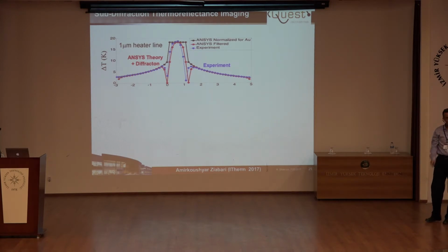So again, Fourier works quite well, up to 1 micron heater. And because of diffraction, what I call filters, the effect of diffraction, and because of the sign change, there is a zero crossing. The red is the modeling, which has been blurred, and the blue is the experiment, and the two match quite well, and the temperature on top of a device matches quite well what we expected.